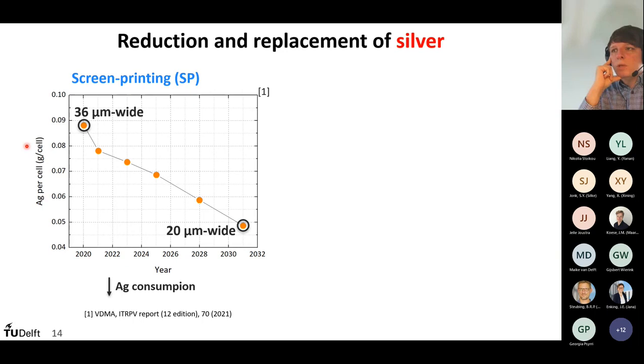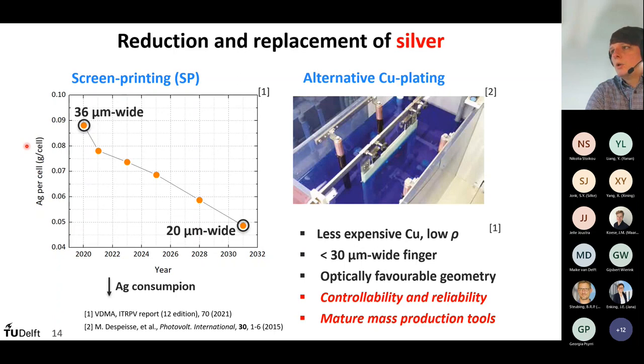And we also have to note that we already reduced silver. So on a per cell level, we were using 70% more silver 10 years ago. So we expect this trend to continue by making smaller contacts. But at some point, the cost is not going to be worth it, and we are working on alternatives, which is certainly copper-based. There are different ways of making the copper contacts. One of them is plating, and these are the things that we optimize for in PV.